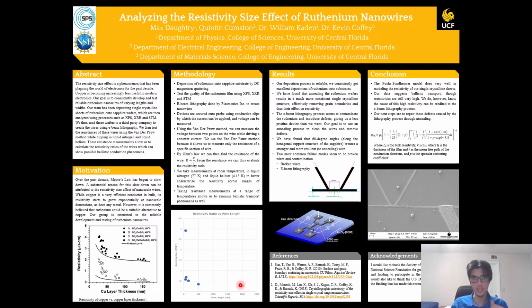Another thing to point out is that this resistivity ratio is plotted versus the length of the wires themselves. Our longest wire here is 2,000 nanometers, and it goes down to 60 nanometers. It seems we observed ballistic transport on a wire 65 nanometers long, and we would expect to observe ballistic transport on the lower side, because essentially we're getting closer to the point where the wire is shorter than the mean free path.